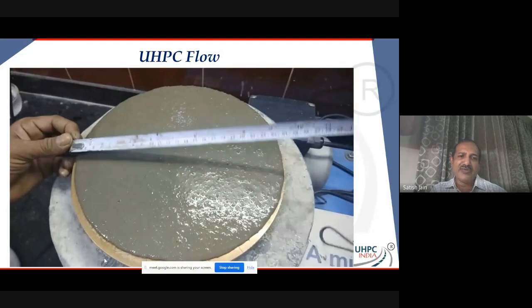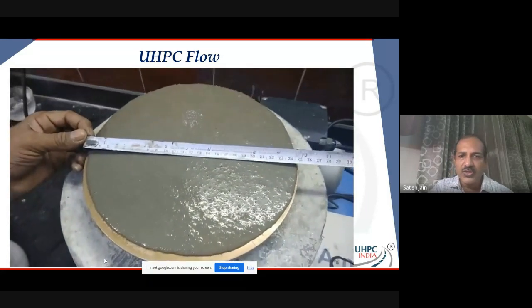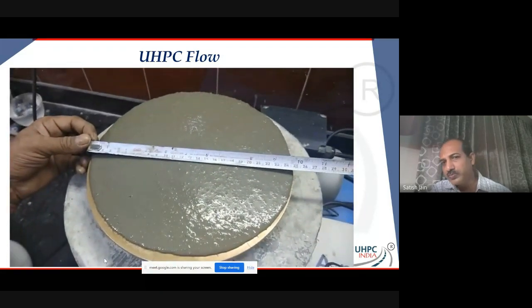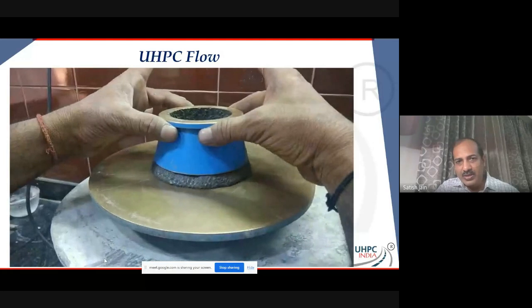Typically you're going to have anywhere from 190 to 240, 250 mm of flow. And once you have this kind of flow, it's just so easy to place UHPC, extremely easy to place. There's another UHPC that is used, and we are going to come to that. That's called UHPC overlay, where you need a little bit of a thixotropic mix, which just doesn't flow off. It is workable, but just doesn't flow off. So we'll come to that.